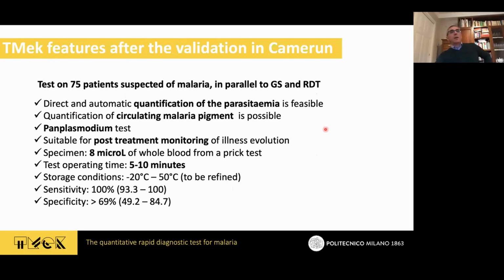So just to tell you that after our pre-validation, what we can say is that really TMek can be a direct and automatic quantification method for the parasitemia. It's really something feasible also according to our test made in Sacco Hospital. The quantification of circulating malaria pigment is possible. What is interesting is the Panplasmodium test, because we have tested on falciparum and also on vivax. That's very interesting for future development. It's suitable for post-treatment monitoring of the illness evolution, which means that you can now follow what happens during the treatment, as in the case of a patient affected by vivax.